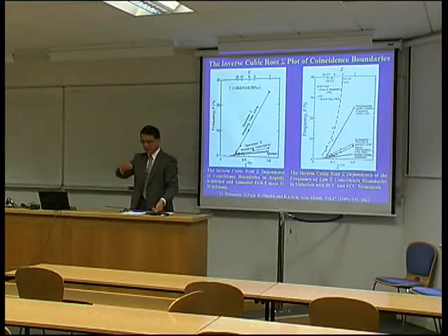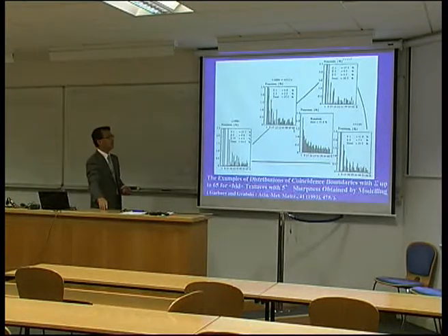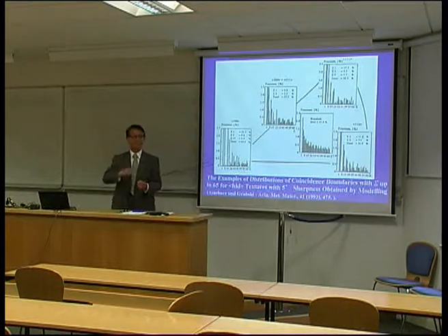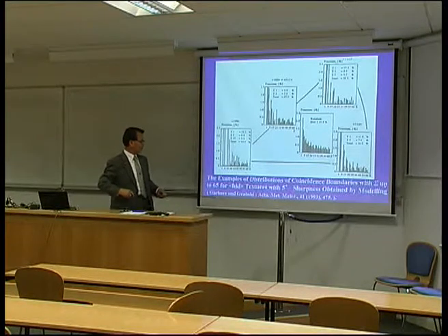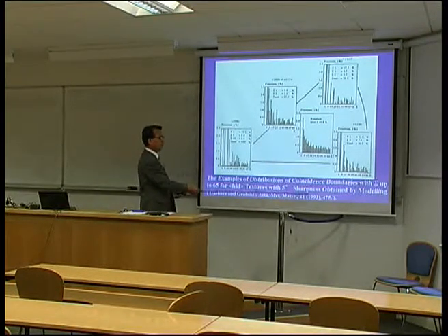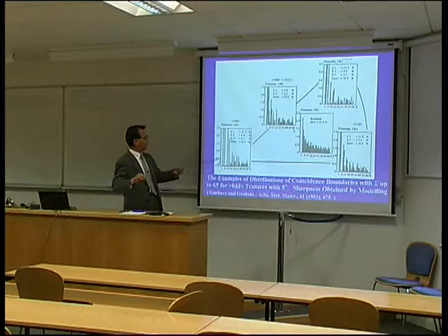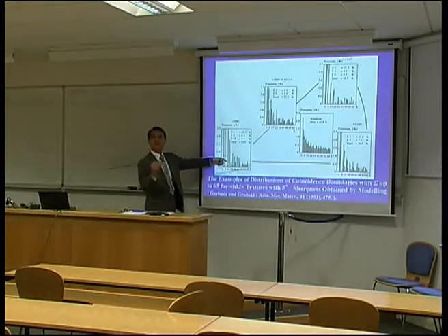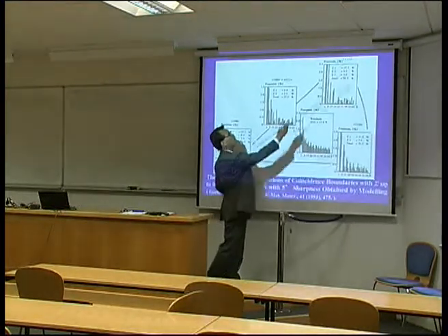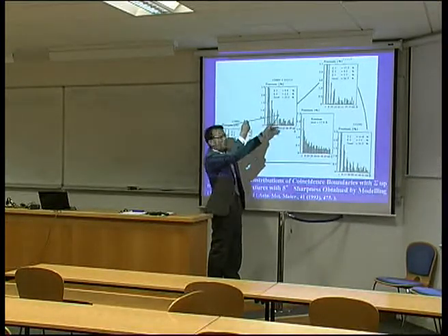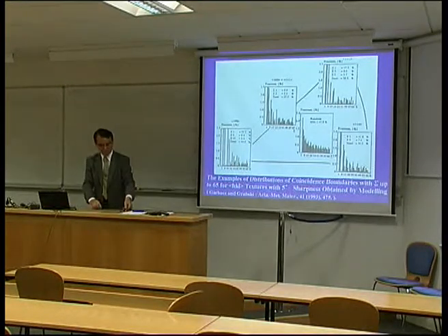There is such a very elegant basis. So now, depending on the sharpness of texture, we can predict the frequency of special boundaries. In this case, Professor Grabski's group already published a theoretical prediction and compared it with our data. If the polycrystalline material has a sharp texture within 5 degrees, a sharp 1-0-0 texture, or 1-1-0 texture, or 1-1-1 texture, or random or a mixture, in this case we can now predict the quantitative fraction of special boundaries.